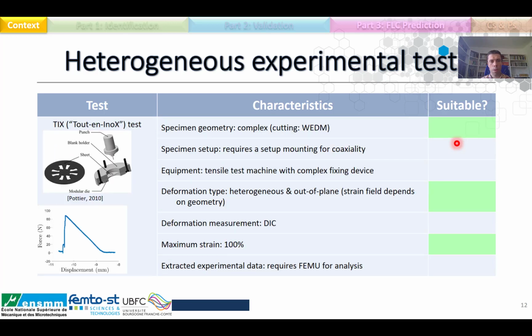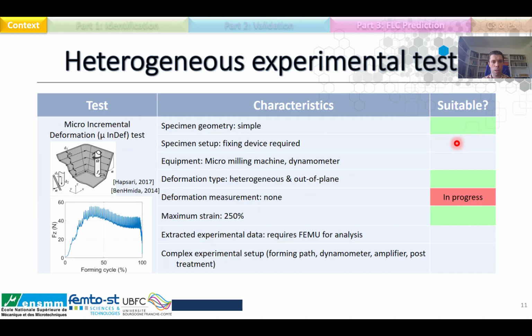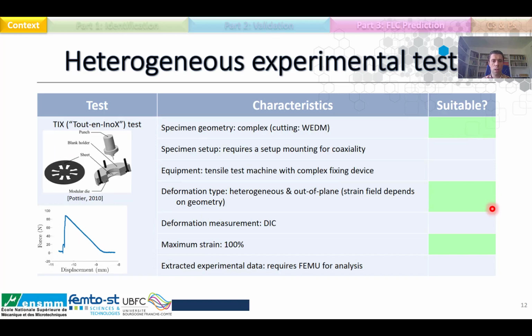We also developed another test because, as you can see, the previous one has one weakness. It's very difficult to use with digital image correlation. So we tried to think about another kind of test which permits the use of digital image correlation. So we went with what we call TIX. This test will be explained later in the presentation, but this test matches all the requirements.